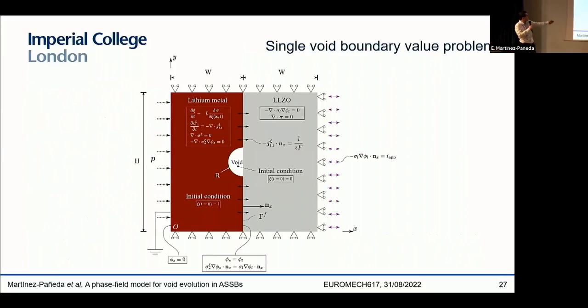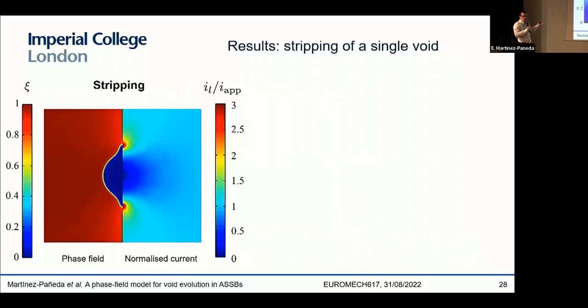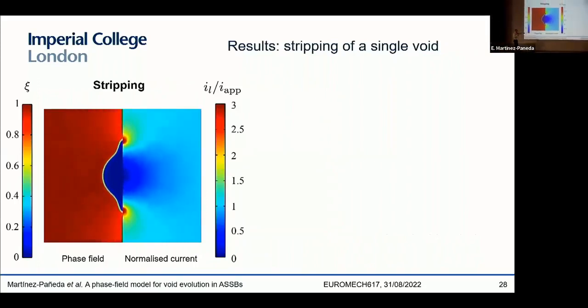And yeah, you can see here superimposed equations that we're solving in each domain. And here you can see some results for stripping. What I'm showing here on the left, these contours are the phase field contours. The phase field is blue, 0 inside of the void, and red, equal to 1, in the solid metal phase. And then what I'm showing here on the right is the normalized current. So this is the local contours of the current density.